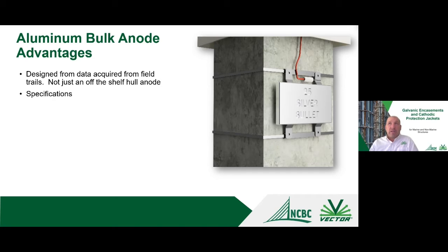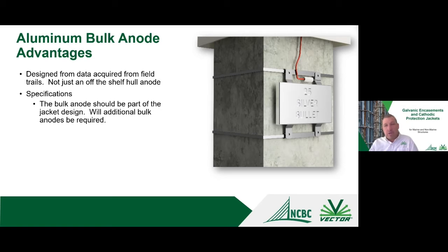So one thing you need to do when you're doing a CP jacket design or writing the specifications is make sure that the bulk anode is part of the jacket design. If you have a very large drill shaft pile that is 60 inches in diameter and goes down 40 feet into the water, you're likely going to need more than one bulk anode. So make sure the bulk anode is part of the jacket design in the design phase. You're not only designing for how high the jacket is going to come out of the water, but also including the bulk anode. It all depends upon how much of the pile is in the water column. With a longer pile or larger pile, you're likely going to require 2 bulk anodes instead of 1.